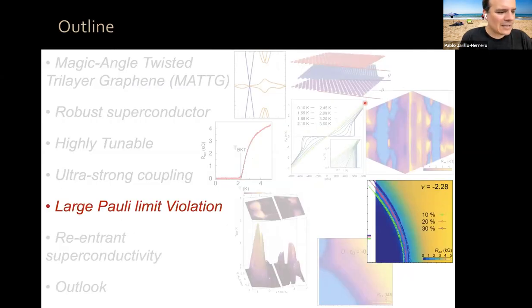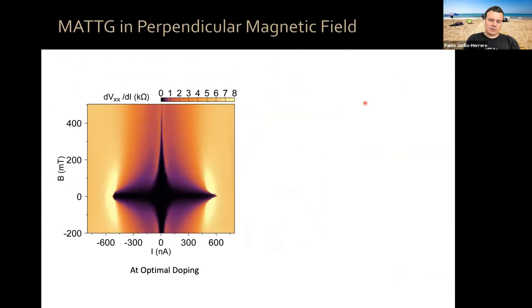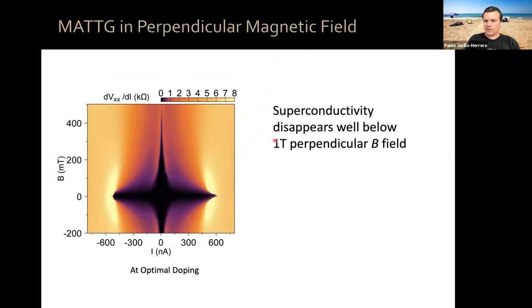In the last 10 minutes or so, let me tell you about the properties of the system in a parallel magnetic field. If we apply a perpendicular magnetic field to magic angle twisted trilayer graphene at optimal doping, it introduces vortices, this orbital effect, which kills superconductivity well below 1 Tesla. Now, because the system is a two-dimensional superconductor,